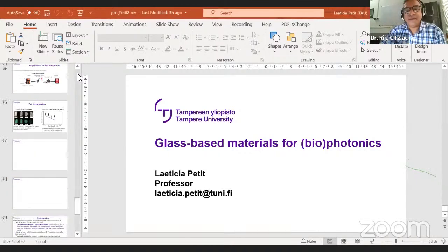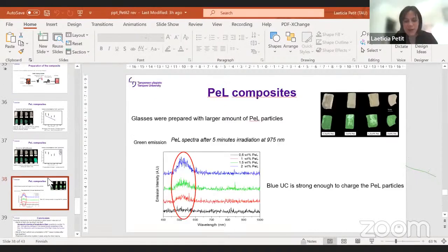Duration. Yes. Where we can use it. So here, when we do it this way, we have the persistent luminescence only for 5 minutes. But this is just the first time that we were doing the composite. So now we know that adding the persistent luminescence using the direct doping method is probably not the best way to do. And this is just to make a bulk.